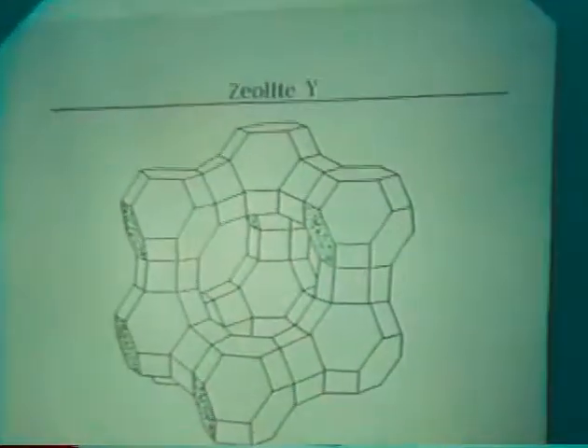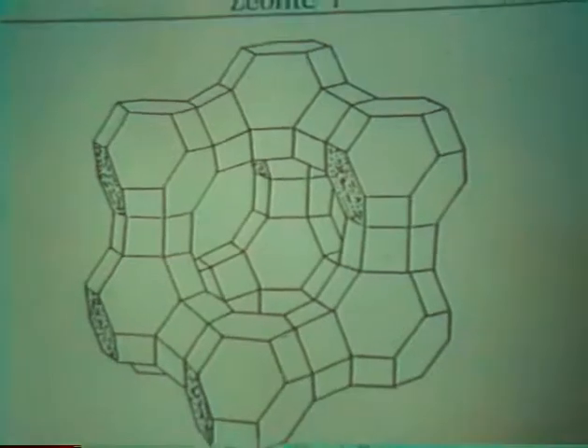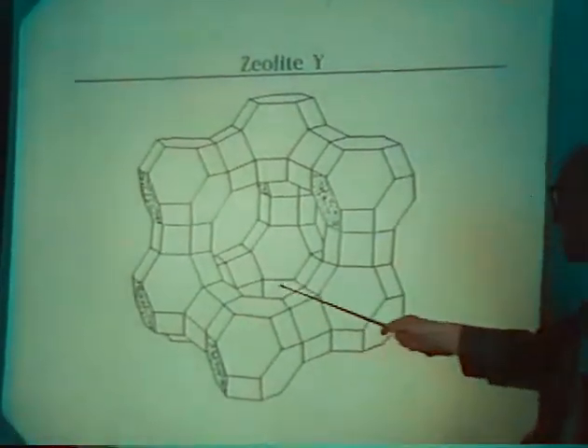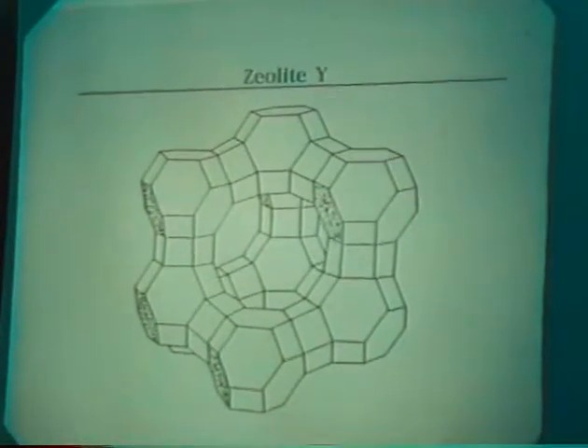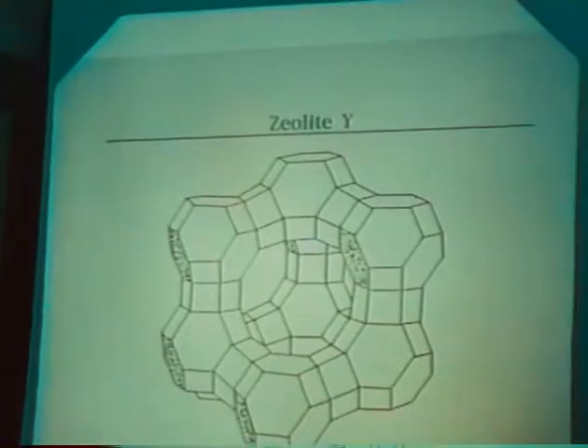In the years since, we learned something about how to manipulate catalysts in zeolites and to control how you get atoms and ions into the cages of a zeolite. We therefore took the faujasite zeolite, which has three types of cages — the supercages, the sodalite cage, and the hexagonal prism. We started this work with the purpose of getting rhodium clusters and manganese ions or other compounds into the same supercage, to see whether this had the desired effect.